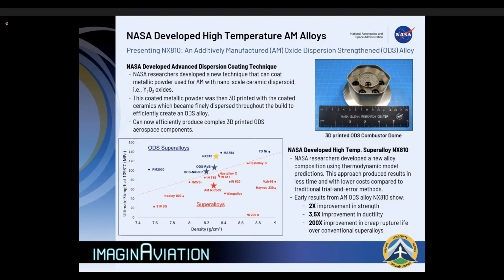And what you can see here on our graph, AM nickel, cobalt, chrome, that is nickel, cobalt, chrome without oxides. And then just by incorporating the oxides, you can see an improvement in your high temperature strength by doing so, basically forming an ODS alloy. And so we were incredibly excited about these initial results. And we also found they were more ductile and provided even better creep strength. All right, but nickel, cobalt, chrome wasn't really the composition that we wanted to stop with.